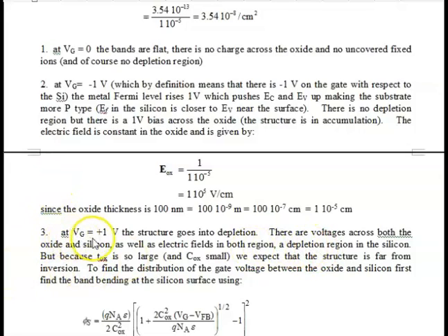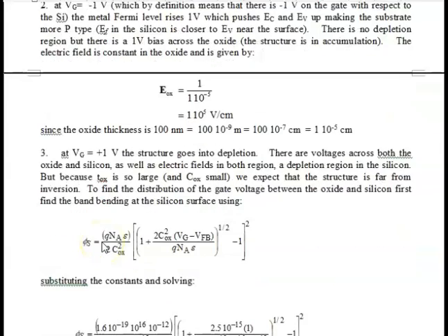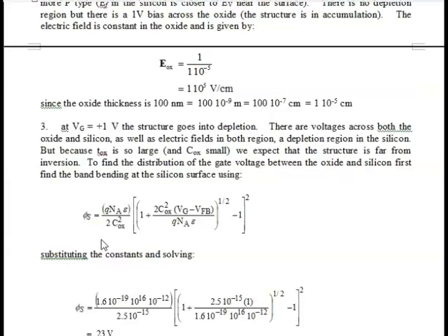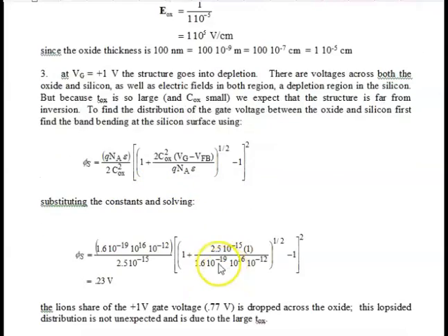Okay, and that's now +1 volt. Well, if I was in accumulation with -1 volt, I can pretty well guess that I'm going to be in depletion with a positive voltage of +1 volt. And since I'm in depletion, I'm probably going to have some band bending. Well, this is the basic formula for band bending, which we've seen quite a number of times, and I put in all the numbers here. The Q is here, the NA is here, this is now not the oxide permittivity, this is the silicon permittivity, 10 to the -12th.